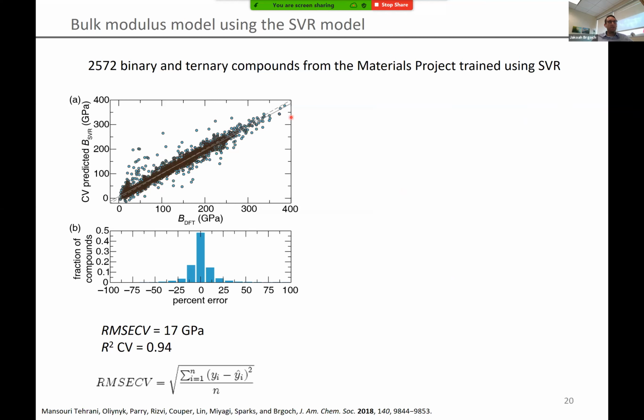The dark regions are where we have a significant amount of data overlapping. If you look at our histogram, you can see that nearly all of the compounds fall within 10% error, or even better than that. So overall we get really reliable prediction. Our cross-validated R squared is 0.94, and our root mean squared error is 17 gigapascals. So this is pretty reliable.